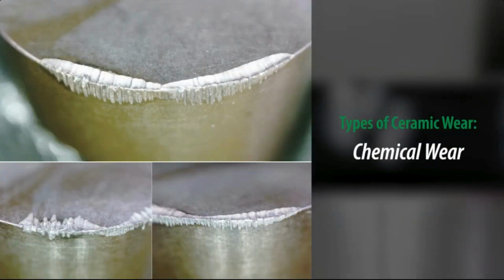In this image you can see chemical wear. Chemical wear is the least common provided the material being machined is correct for the tool. It occurs as a result of chemical interaction between the tool and the workpiece at elevated temperatures. It is expressed as crater wear on the rake face and aggressive flank abrasion and striations.